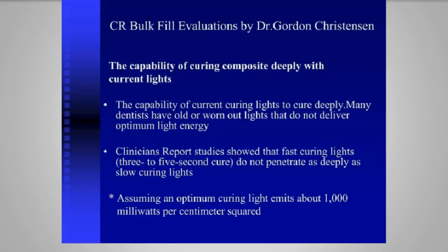Now, let's look at a clinical report from Dr. Christensen. What he found for bulk filling is basically related to the curing lights, because many dentists have worn out curing lights. They haven't been calibrated. They haven't been tested, and they don't deliver optimum energy in the spectrum of light to cure the material. And according to Dr. Christensen, the 3 to 5 second cure doesn't penetrate as deeply as the slower curing lights. And we're assuming that all curing lights meet a minimum standard of 1,000 milliwatts per centimeter squared.